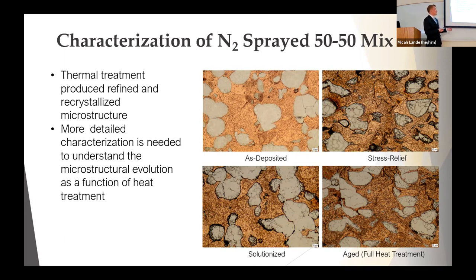This unfortunately was one sample we weren't able to look at with SEM, and that's more future work that we would like to do, because that's of particular interest. If we're talking about creating a bimetallic layer or a bimetallic solid with this stuff, we really want to know, if we have eta-phase growth, is it happening at the same time at these boundary layers in between our copper alloy and our HR1 alloy, or is it just in the HR1 alloy? Those are things we unfortunately ran out of time for. However, that is on the docket for future research.